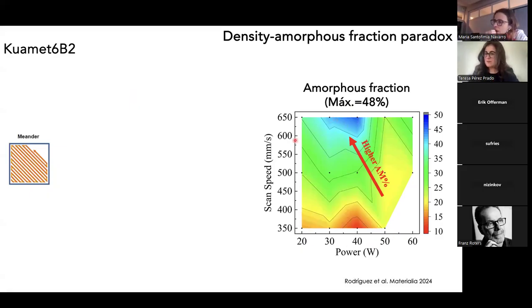So again, the same processing window, scan speed, power. And the first bad news is that the maximum amorphous fraction we can get is 48%. This is very, very far from our target, which was 100%. And then here, this arrow just marks the direction, within the processing space that we are exploring, of increase of the amorphous fraction. So amorphous fraction increases with higher scanning speed and lower power.